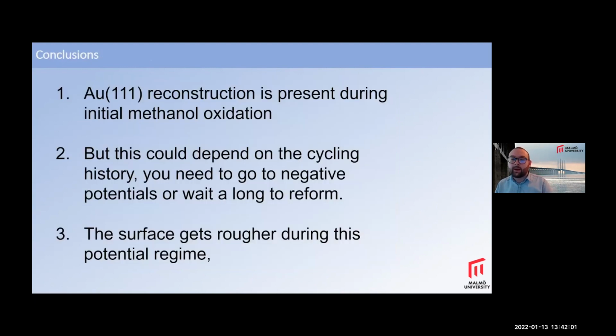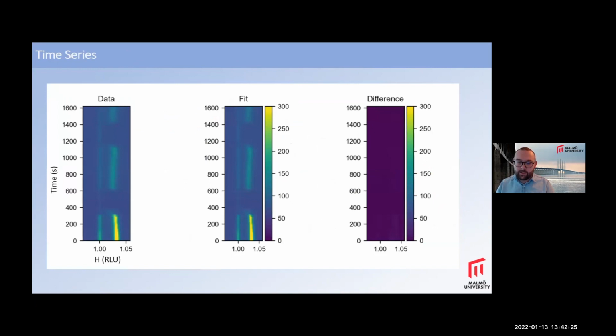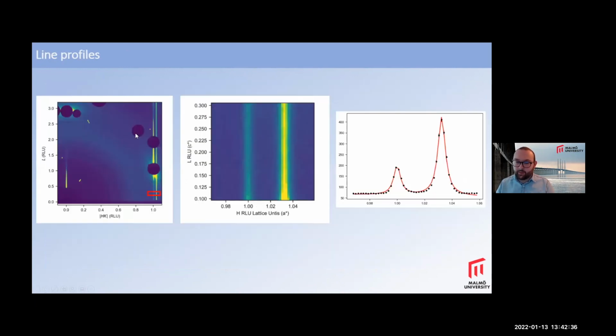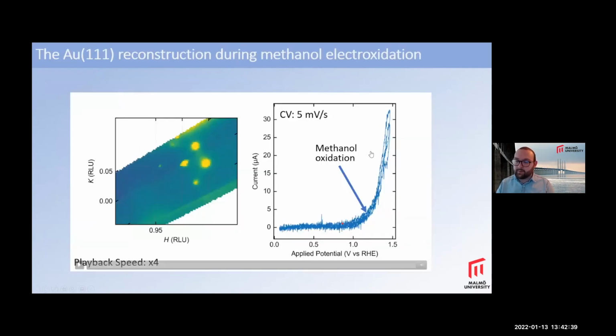So in conclusion, the gold 111 reconstruction is present during the initial stages of methanol oxidation. But you have to be aware that the surface really does depend on your cycling history, and you have to go to really negative potentials to reform the surface reconstruction. And the surface gets rougher during this potential regime. So you can see from here that you have a very bright signal in the initial cycles, but it's getting weaker. So you're very quickly roughening your surface if you go to these high potentials.